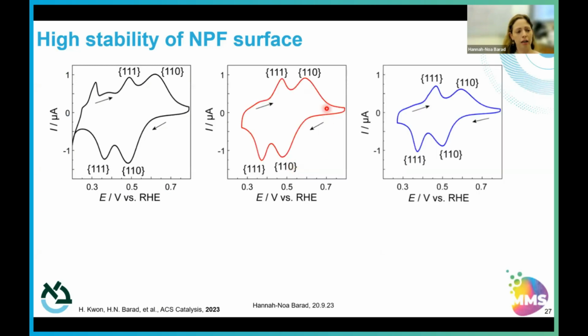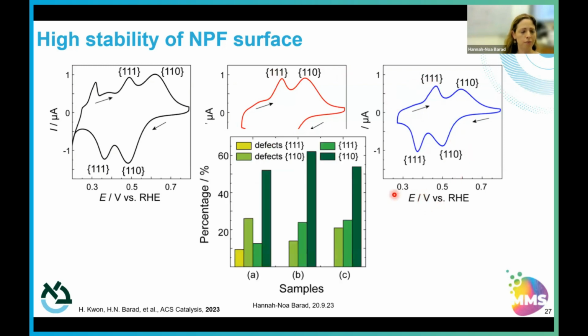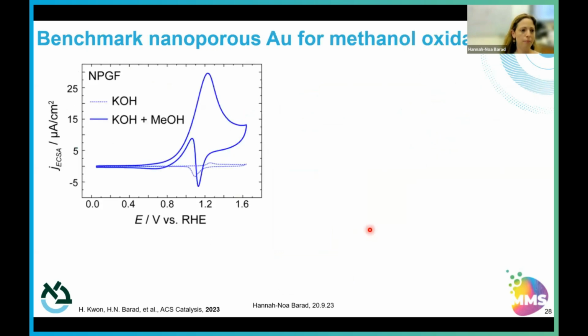And if we look at acidic and alkaline treated nanoporous gold mesh films, so we treat these and then we do the UPD on them, you can see immediately that we're reducing the amount of defects, but we still maintain these active sites in 111 and 110 planes. And if we compare the areas of these different peaks, you can see that the 111 peaks completely disappear after treatment, but we still remain with these 110 defect sites, which is not a bad thing. We want to have defect sites and we want this high curvature and defect sites because they provide more catalytically active sites. So we then tested this for methanol oxidation reaction in 0.1 molar methanol.